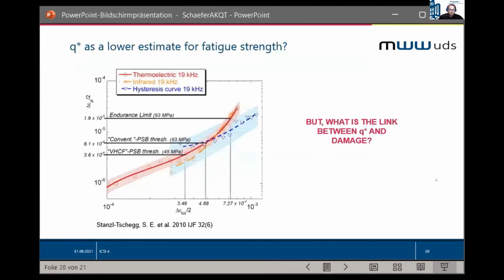But one question remains: what is the link between this heat generated per load cycle at the knee point and damage? And this work by Stanzl-Tschegg showed that in the fatigue strength regime, there are several processes that influence the fatigue strength. The knee point is attributed to the onset of dislocation motion, but this is unfortunately not identical to damage. Therefore, we can assume that the knee point stress amplitude is just a lower estimate for cyclic dislocation motion and hence for the fatigue strength and not the fatigue strength level itself.